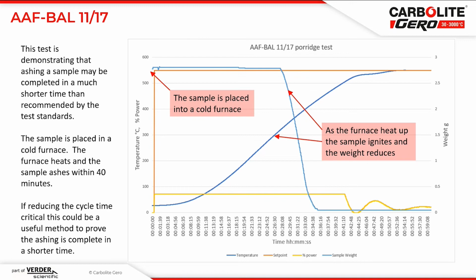So you can see there the blue line that's falling, it's the lighter blue line that drops, and you can see that's dropping whilst the furnace temperature is around the 300 to 400 degrees C mark. The weight is shown on the right-hand scale of the graph. So that's the weight falling. And we end up with about 2% mass left in the sample. So if reducing the cycle time is critical, this could be a useful method for proving the ashing is complete in a shorter time. This allows a user to have evidence that their process is complete in that shorter period of time.